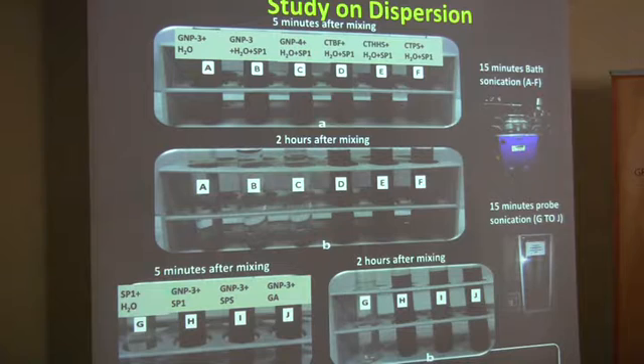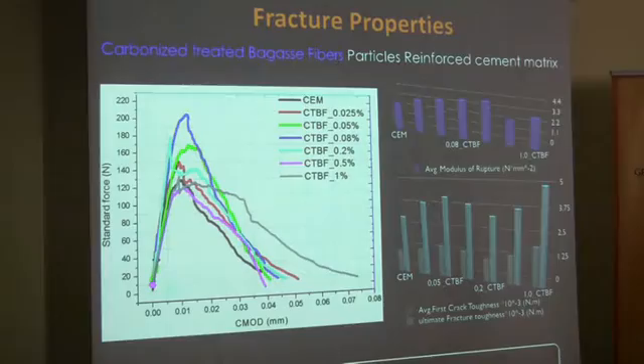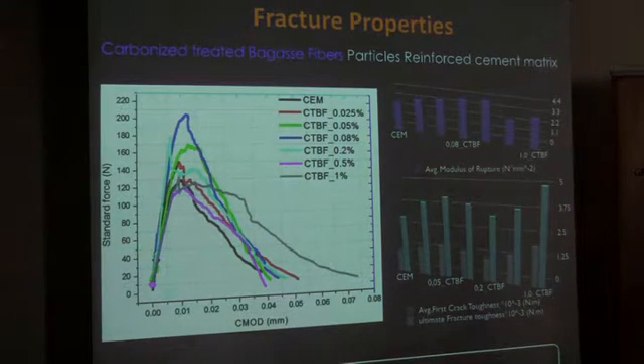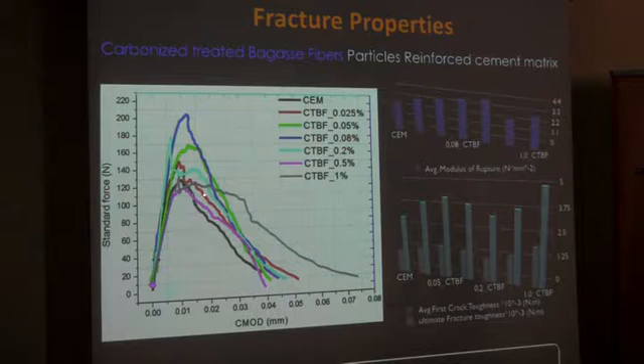We spent a lot of time in particular studying the dispersion of this carbonaceous material in the water. The water was, of course, needed to prepare the concrete. What we can see, for example, from the addition of carbonized material obtained from bagasse fibers, in black you can see the curve, the force with respect to the displacement, and the colored ones are the other curves obtained by varying the percentage of inerts that we add.